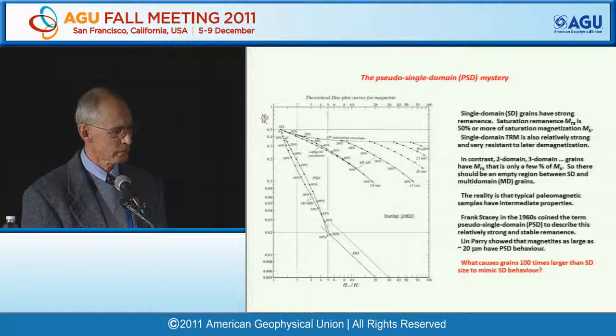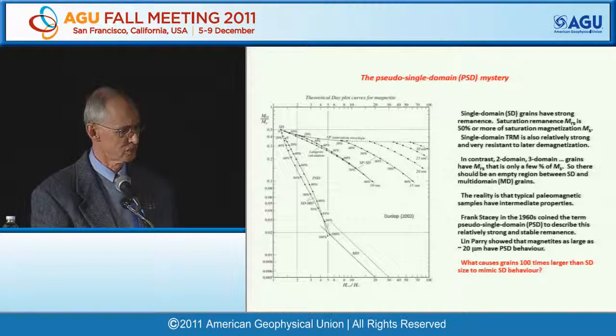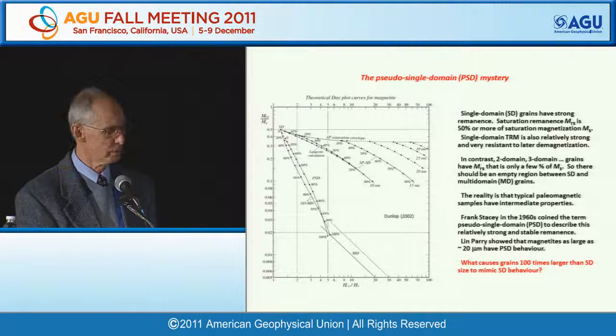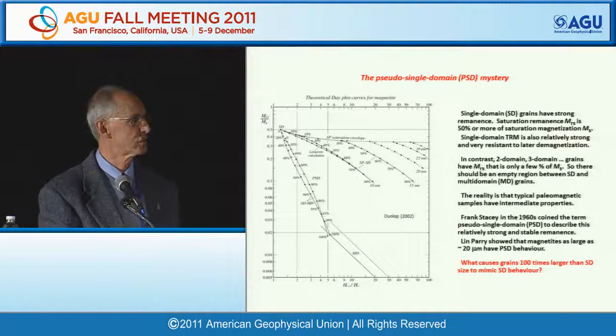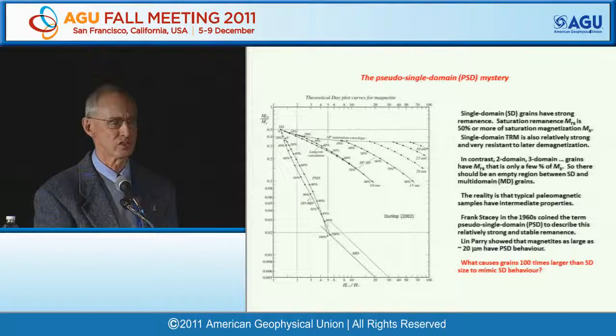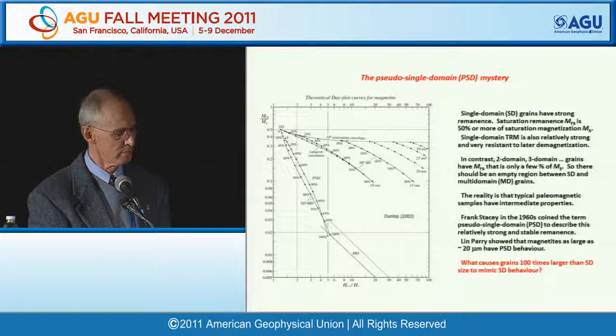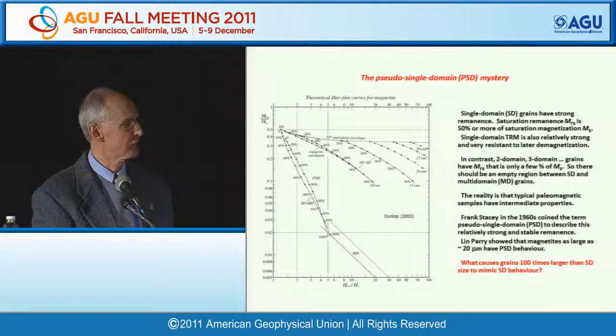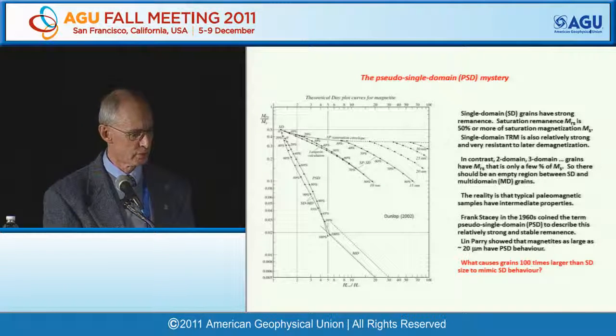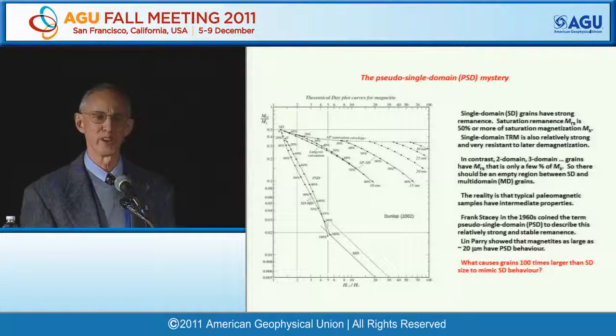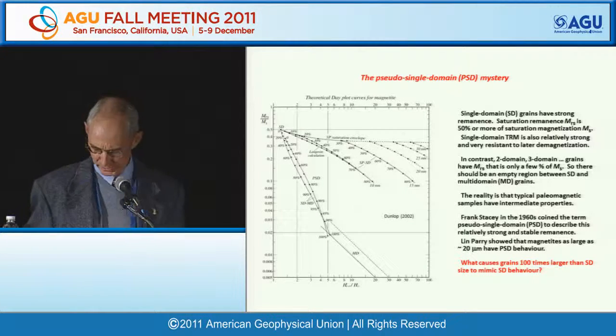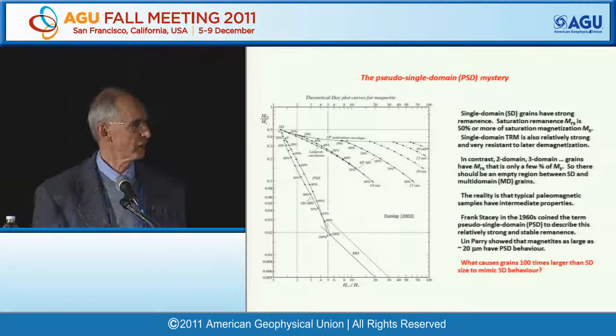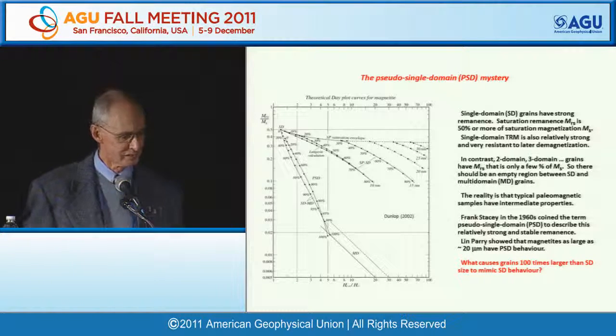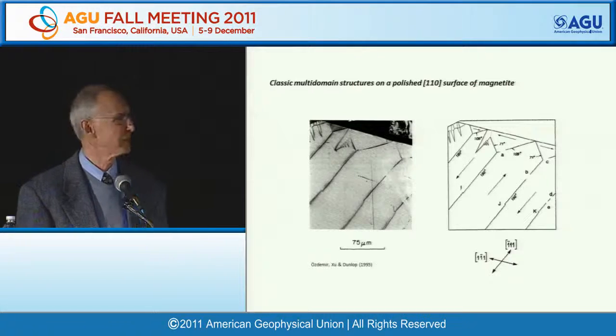So we have a serious problem here, that instead of an empty region, the reality is that typical paleomagnetic samples have these intermediate properties. Frank Stacey knew about this back in the 1960s. He was the one who coined the term PSD. And shortly after, Lin Parry showed that magnetites as large as 20 microns could mimic single domain behavior. They were also PSD. So what causes these big grains to mimic single domain behavior?